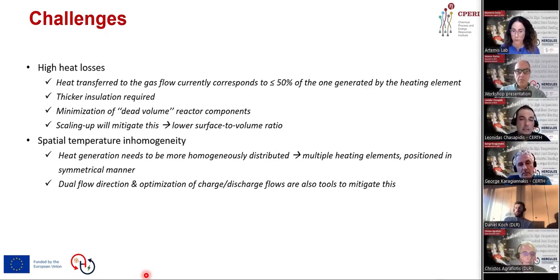However, as with any scale-up step, several challenges have emerged. So the two main ones are the high heat losses and the spatial temperature inhomogeneity within the reactor. The heat losses are mostly associated with the external insulation and the relatively high surface to volume ratio of this pre-pilot system. Temperature inhomogeneity is partly due to the geometry and the position of the heating element, which can lead to uneven reduction and oxidation, especially near the outer regions of the material.